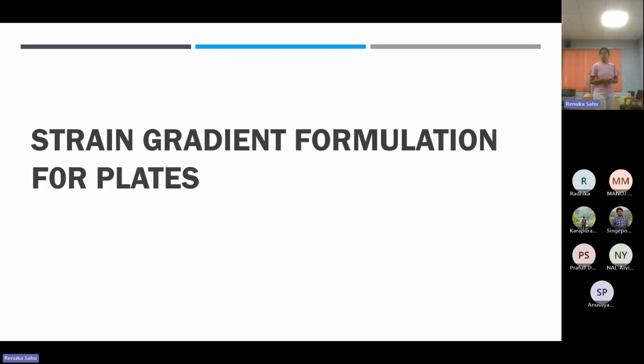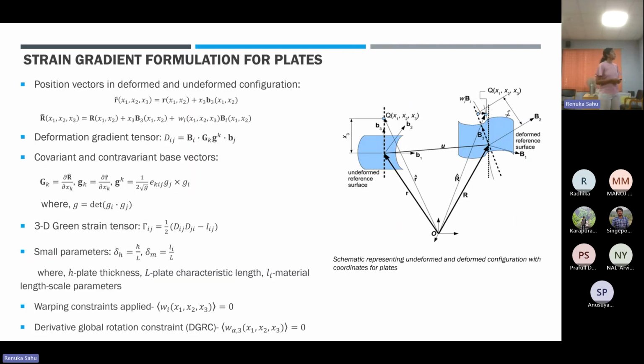Now we come to the strain gradient formulation for plates. Again we start with the same kinematic relations, but for plates we have different position vectors in deformed and undeformed configuration. We obtain the deformation gradient tensor and move forward to the 3D strains. For plates, the small parameters taken are the plate thickness to the plate characteristic length, which can be either the length or the width, and the material length scale parameter to the length ratio.